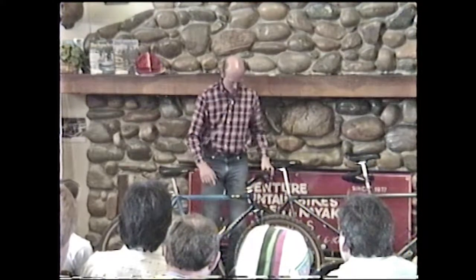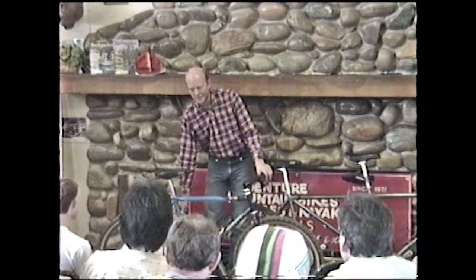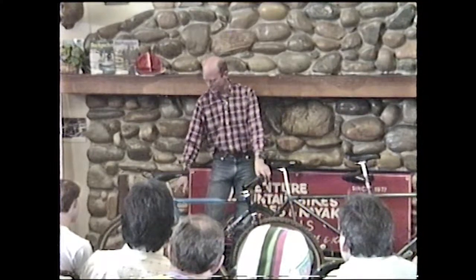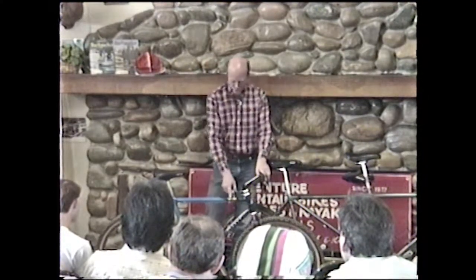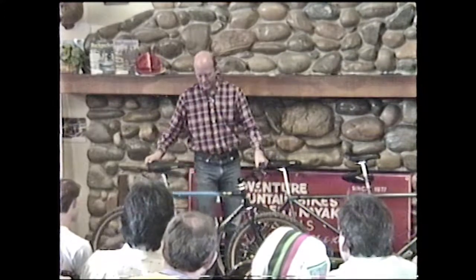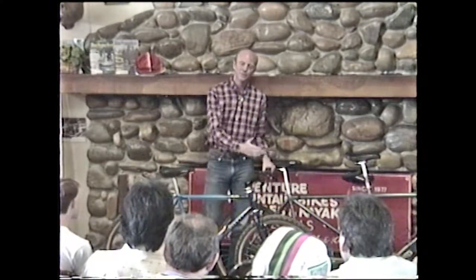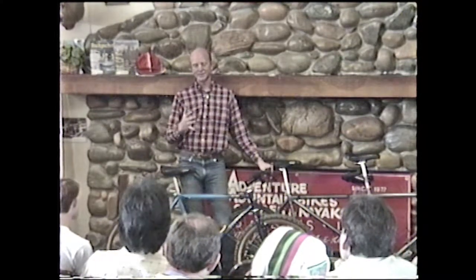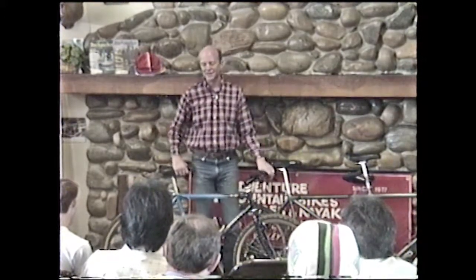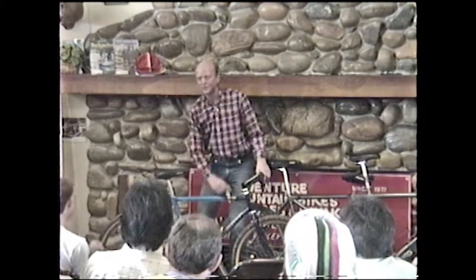That's the quad-butted tube. Top tube is actually a double-butted tube. Seat tube is a single-butted tube. That is, it's about 0.8 here and becomes 0.6 along here. This one is 0.8, becomes 0.5, 0.8. So the idea here was that the whole front, I wanted to make the bike from this portion forward real stiff, especially torsionally, laterally. From this end back, I actually went a little bit looser than I'd gone before. I'd gone back down to 19 millimeter. It used to be 22.2.